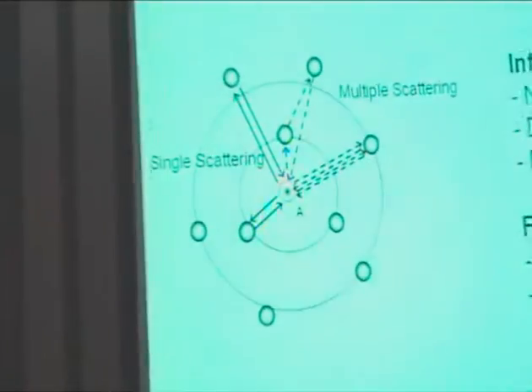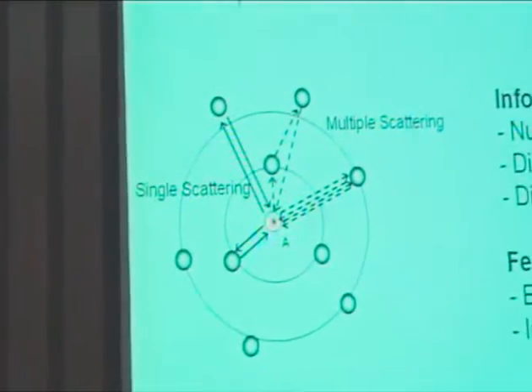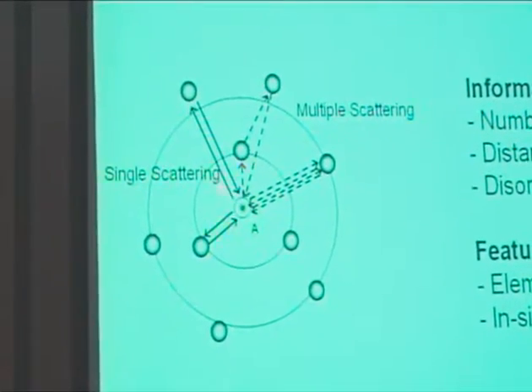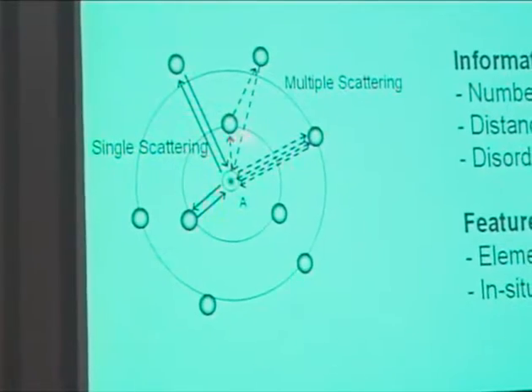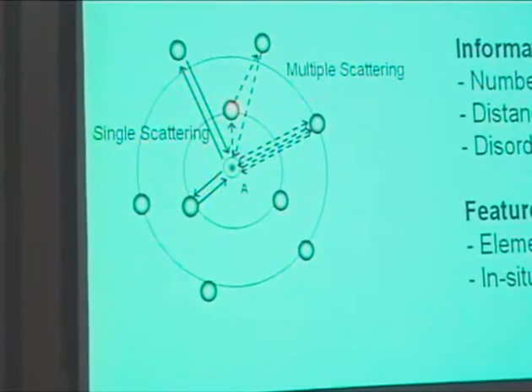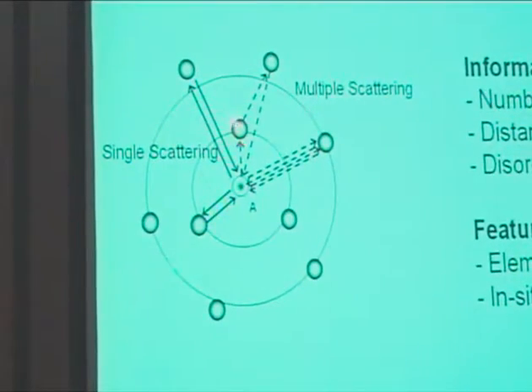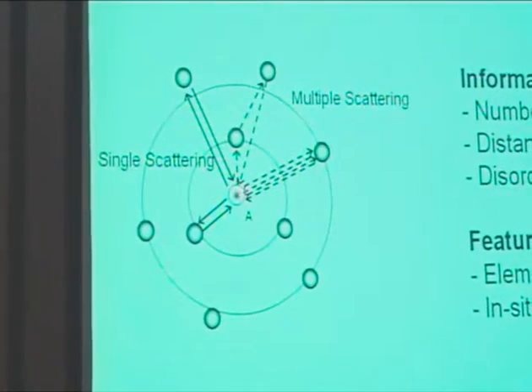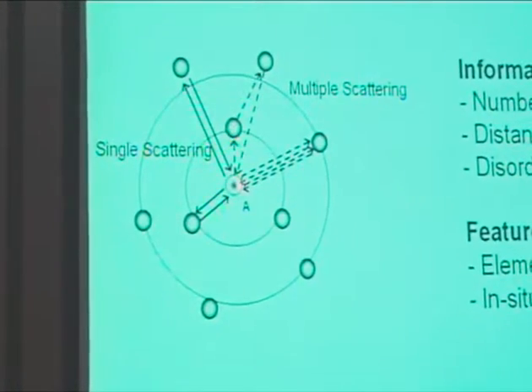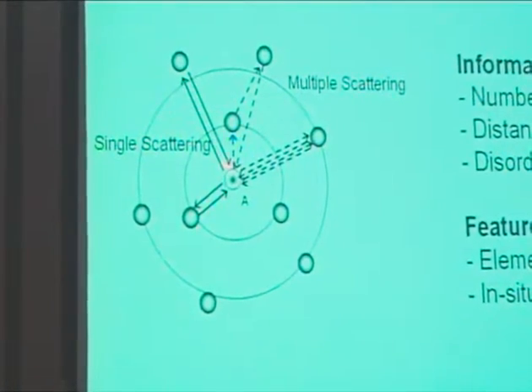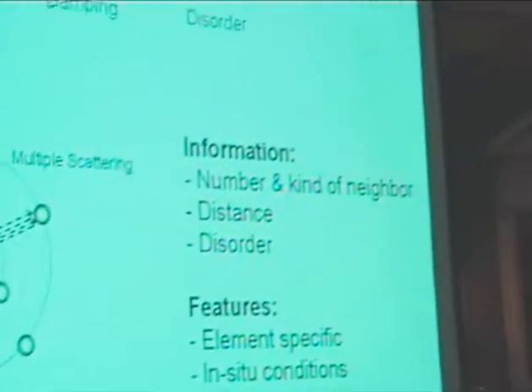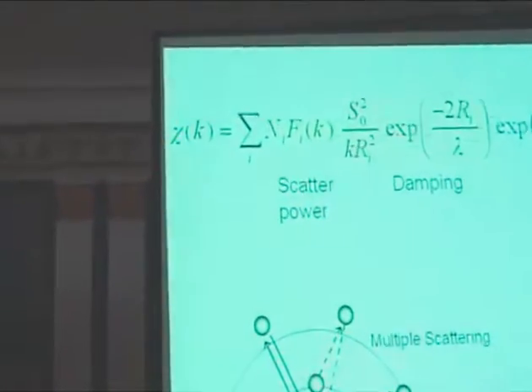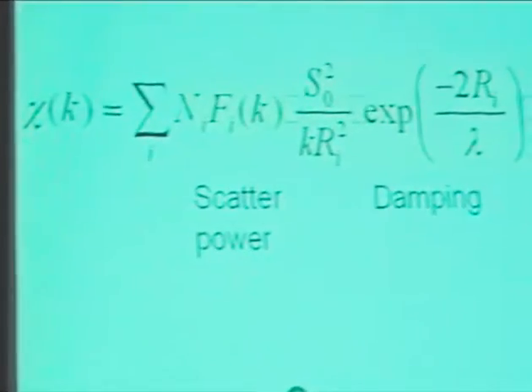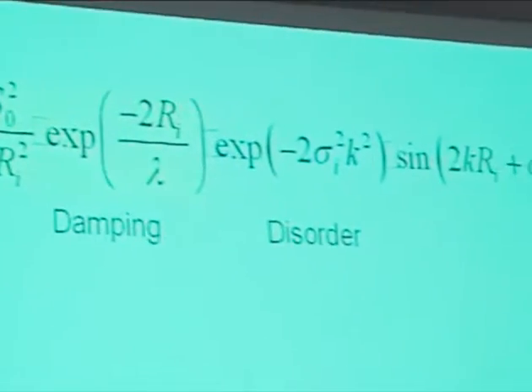And in another type of pictorial view, here is your original atom, here you kick out your electron, and now the electron goes out as a spherical wave, and it bounces into the neighboring atoms and is backscattered. So you get an interference effect between the outgoing wave and the backcoming wave. So in a classic effect, it's like throwing a stone in the pool and you see the ripples. And you can have multiple scattering, you can have single scattering to the first shell of neighbors, to the second shell of neighbors, and so on.